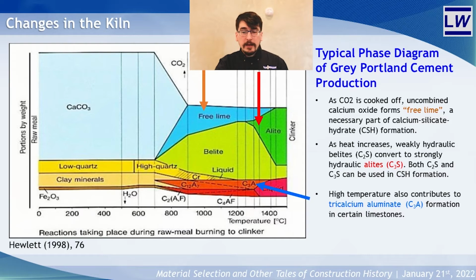Free lime is the amount of calcium oxide available to react with silicates when hydrated, and is formed when carbon dioxide begins to be driven off from limestones above 800 degrees centigrade. Tricalcium silicate, also known as alite or C3S in cement notation, is a complex fusion of oxides containing silica and calcium, and is responsible for the formation of calcium silicate hydrate, or CSH in cement notation. This is what gives Portland its strength.